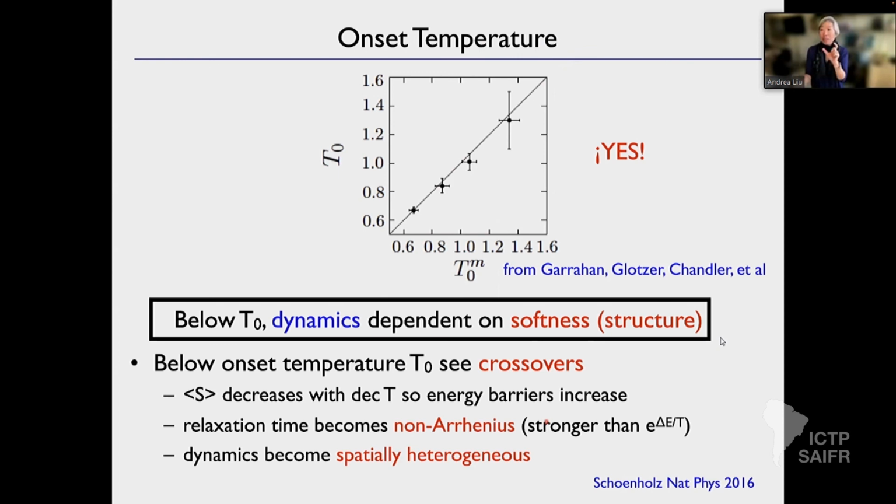It turns out softness becomes just the number of contacts, the coordination number Z. So the local coordination number in high dimensions is softness: particles with lower coordination are softer. So that is something that potentially you could treat with this RSB approach, and try to reconcile all of this. It would be lovely if they did that.